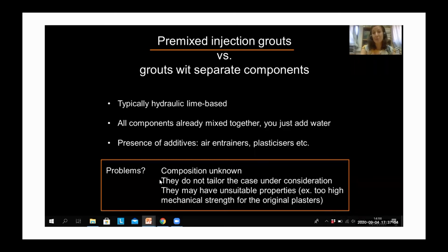They are premixed, so they're always like that. So what does it mean? That they do not tailor the case under consideration. You just have a standard material. You can choose among others, that is true, but it's a standard material to apply to potentially very different cases. And this is very important. They may have unsuitable properties. For instance, as they're hydraulic lime based, quite often, not always, they may have too high a mechanical strength compared to the original materials. So we need to be very careful about these things and take them into consideration.